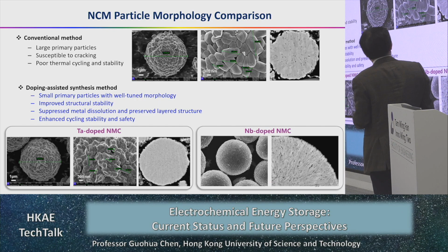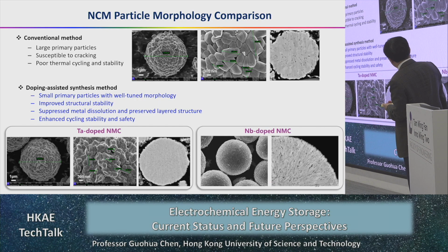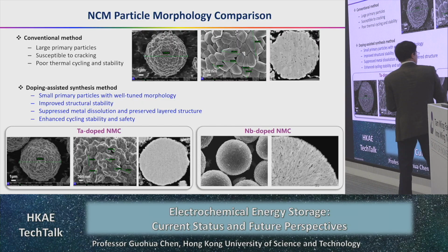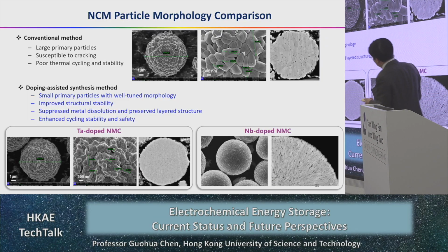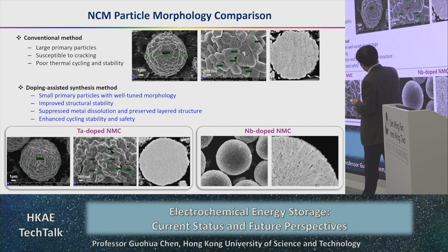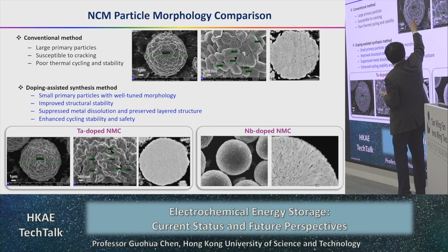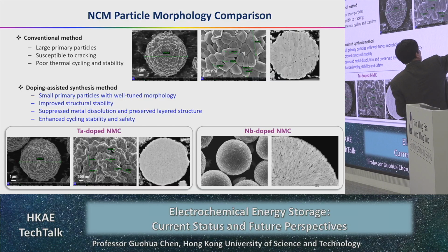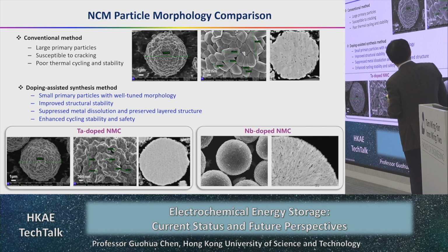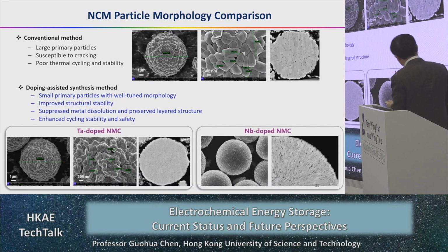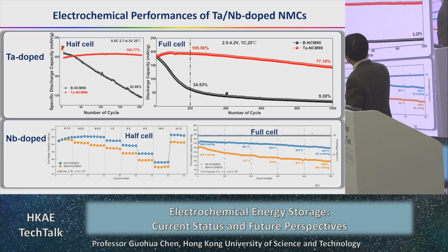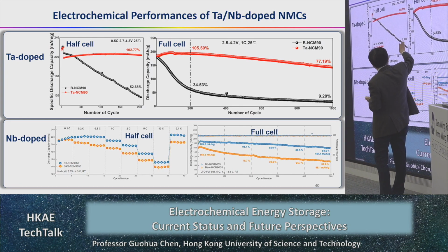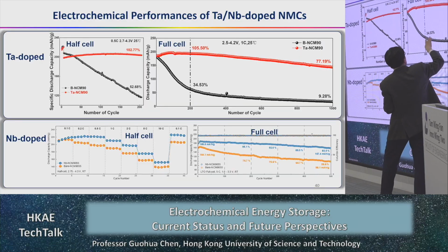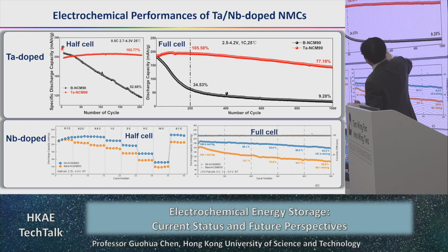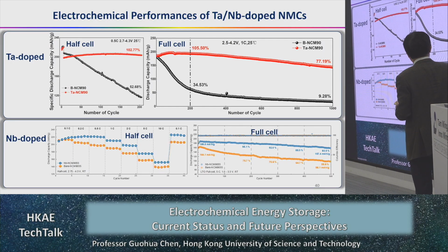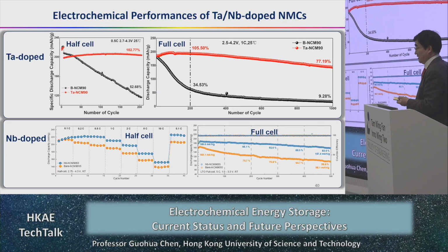NCM particle morphology change by doping. We have tantalum doping and also niobium doping. Without doping, you have the shape like that. But after doping, we would have a longer, needle type of structure. And then you see the performance comparison. This is without doping, and that is with doping. With doping, we can significantly improve the performance. Half cell and full cell tell the same story.